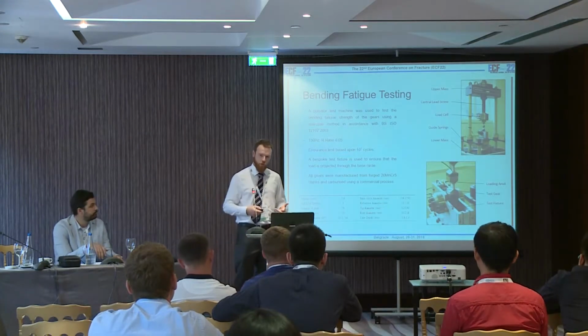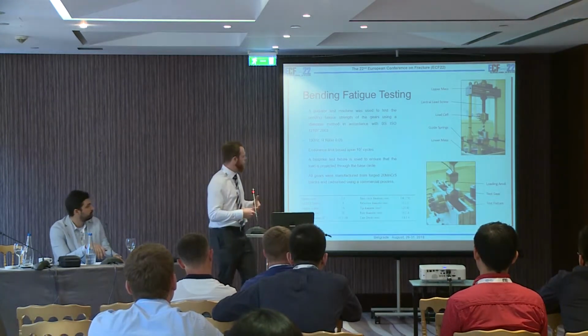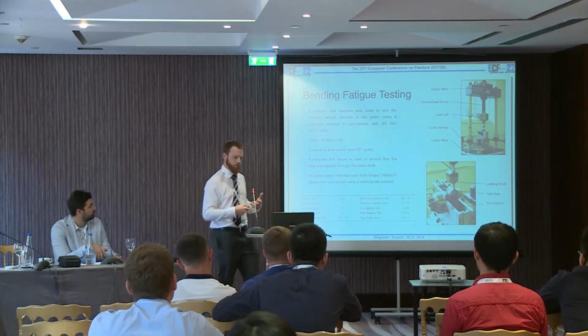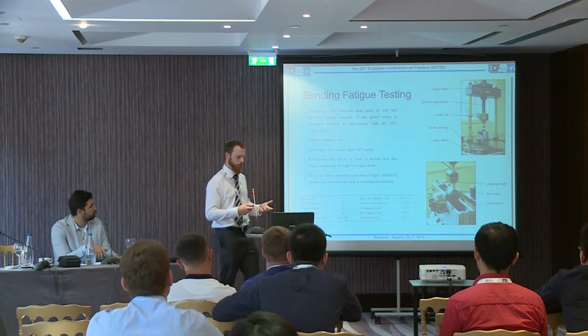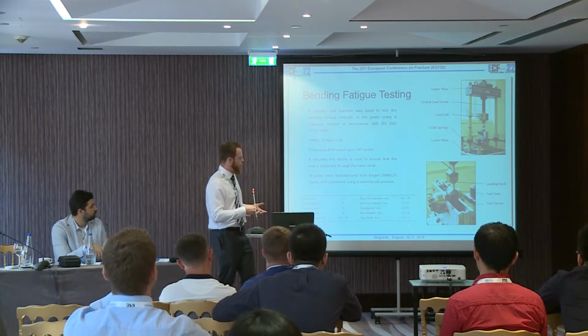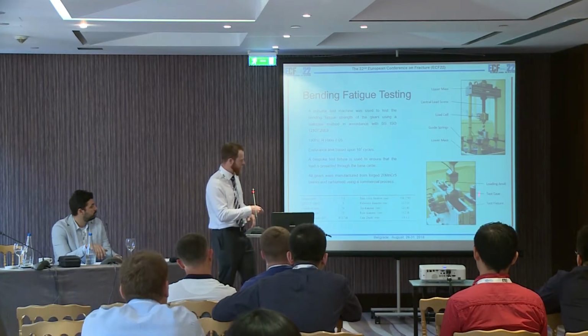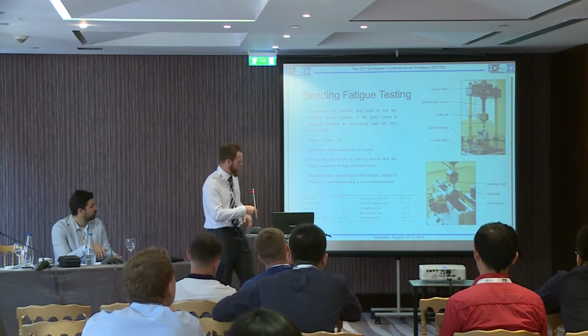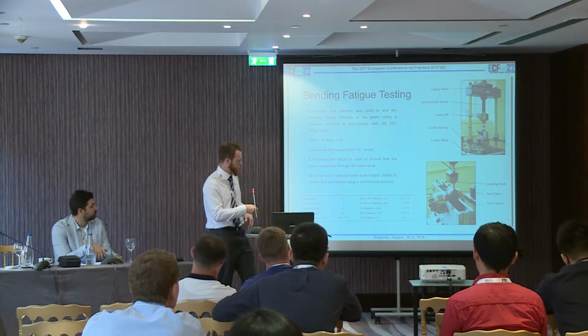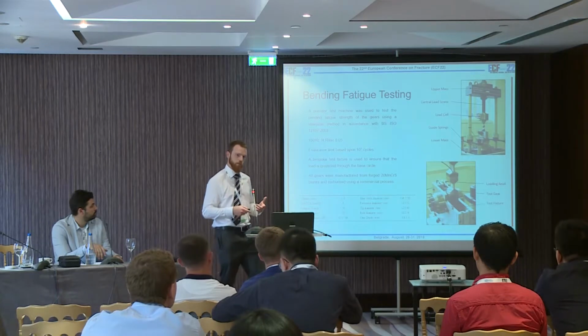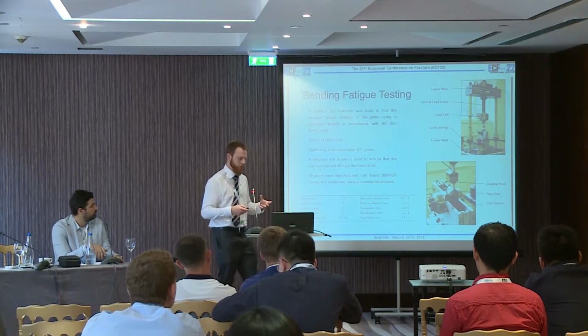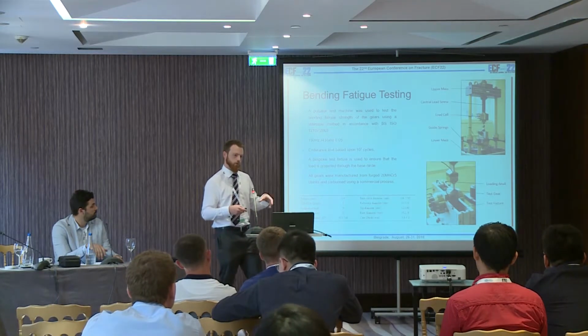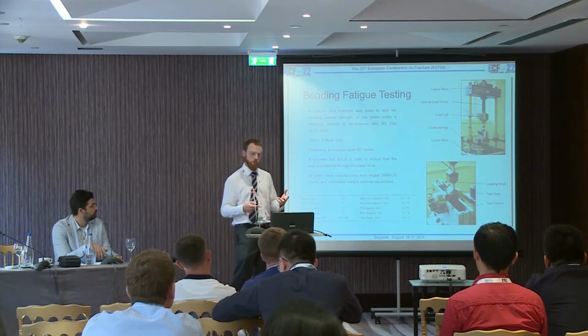So the test method we use to evaluate the bending fatigue strength is a pulsator method. This is a resonance test machine, and we use a staircase method for the test procedure. The key thing about this machine is the design of the fixture that you can see down here, and we need to guarantee that the load is being transferred through the base circle of the gear, and that ensures that this is very applicable to what the gears actually see when in operation.